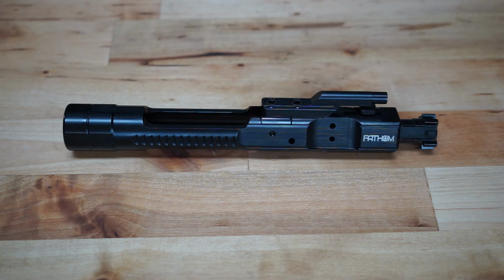And this process is done at subcritical temperatures, so distortional and dimensional changes are virtually non-existent. The part is then placed in a proprietary salt bath, and that salt bath oxidizes the surface of the metal. The oxidation results in the black iron oxide layer you see on the BCG. Below the iron oxide layer is something called a nitrogen diffusion layer, and that layer is 100% treated metal. The nitrogen diffusion layer penetrates into the metal roughly 4/10,000ths to 8/10,000ths of an inch deep.